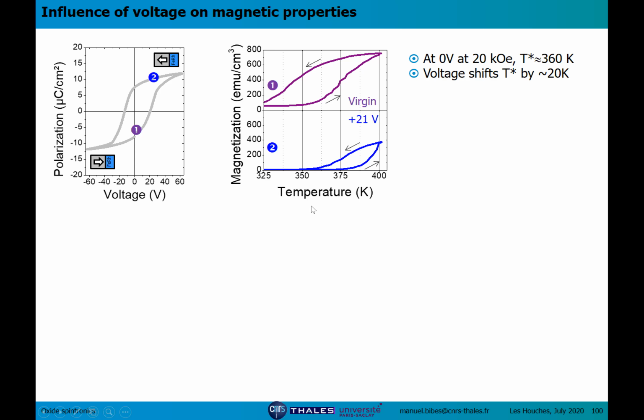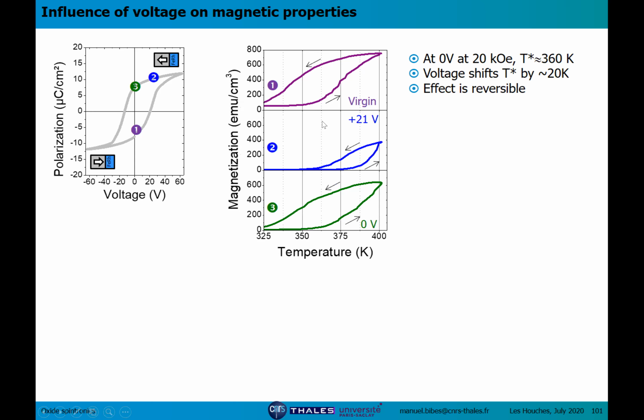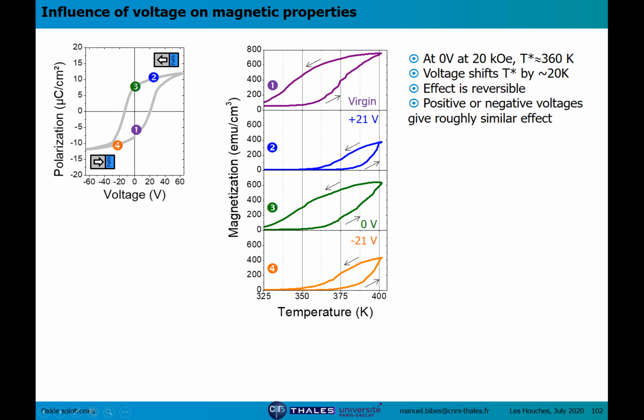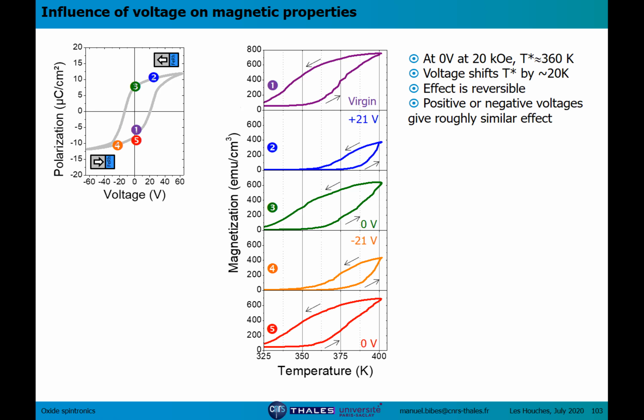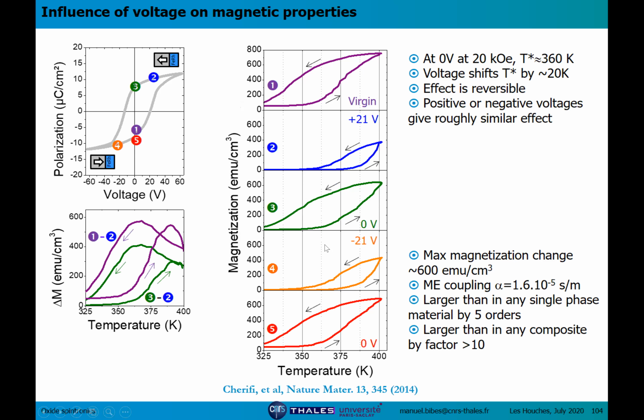And then we go back to 0 and we recover something that looks like the virgin curve. And if you apply now minus 21 volts, we again see the shift towards larger values. And then we can come back. So we have a clear, strong effect of the electric field on the transition temperature. And if we sit at a given temperature, we are going to see a strong variation.